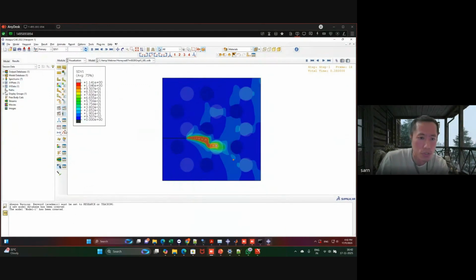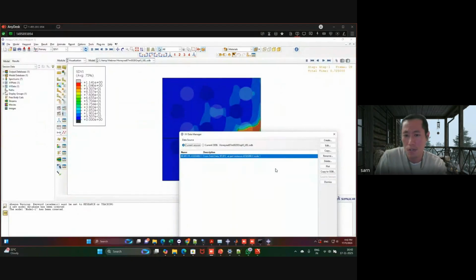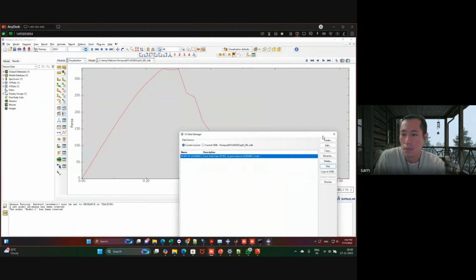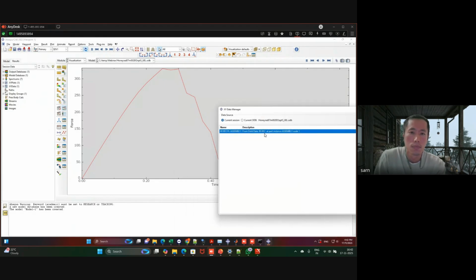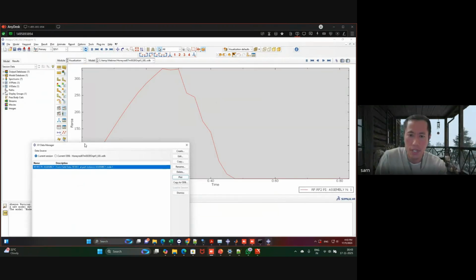And I will also show you the load versus displacement plot. As the displacement increases, the load increases, and at this point the crack starts to appear, and then the load drops, and we have these kinks on the load versus displacement plot. But in this case it is a load versus time plot. These kinks are happening because